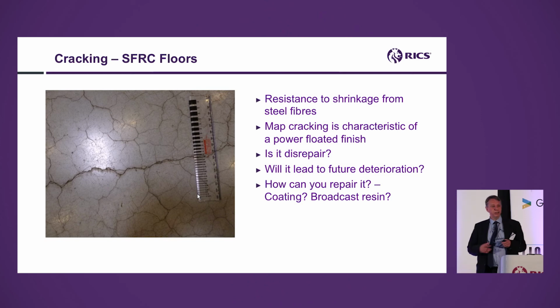If you don't like conventional reinforced slabs, you use steel fibre reinforced, because you can lay much larger bays in one go. These are highly engineered floors. They're not just subject to normal mathematics, if you like. They're a particular product. And this was actually a floor in a very, very large distribution warehouse in Belgium. This wasn't a dilapidations claim as such, but we were involved in a wrangle between landlord and tenant over the cracking. And you can see that there's what I've termed very extensive map cracking in the surface.